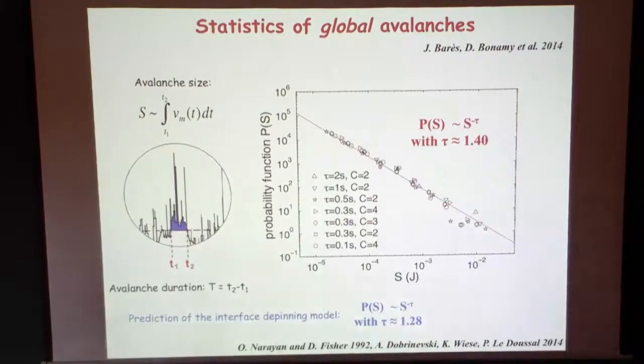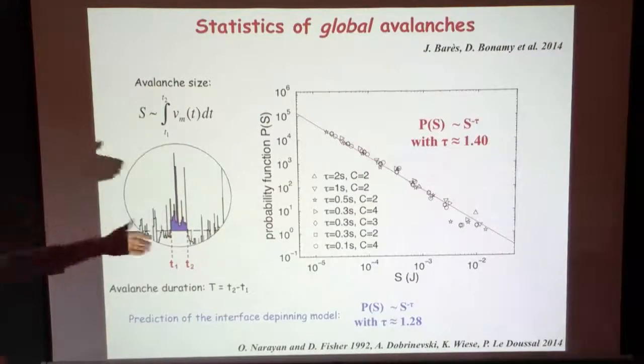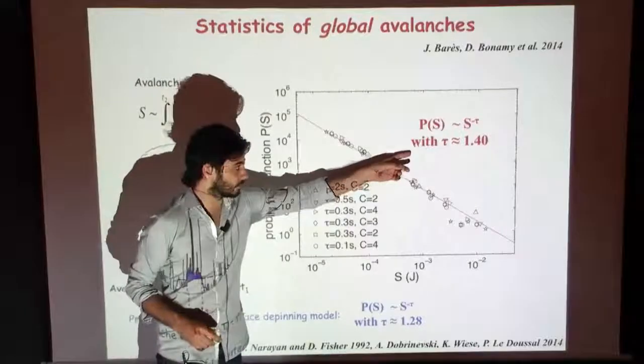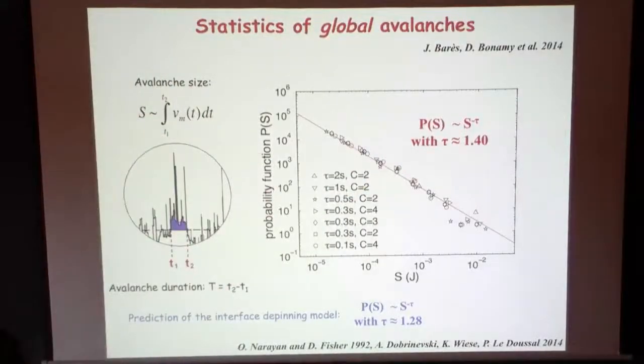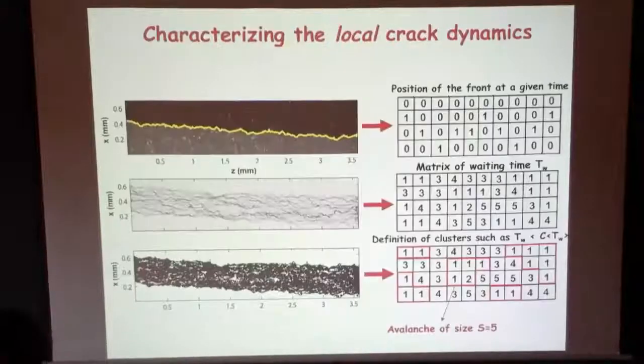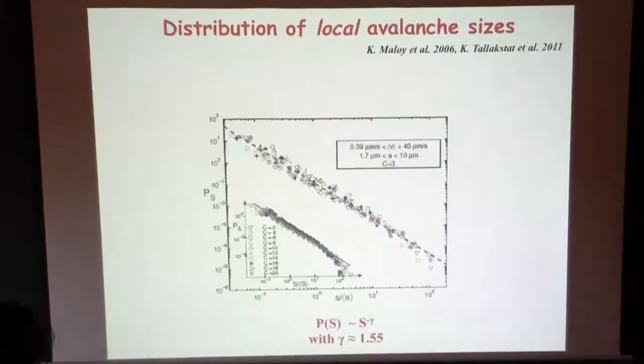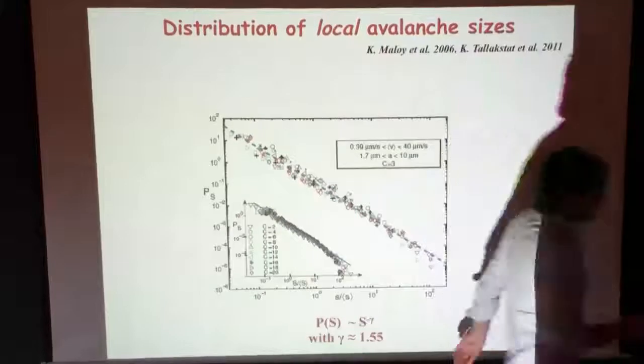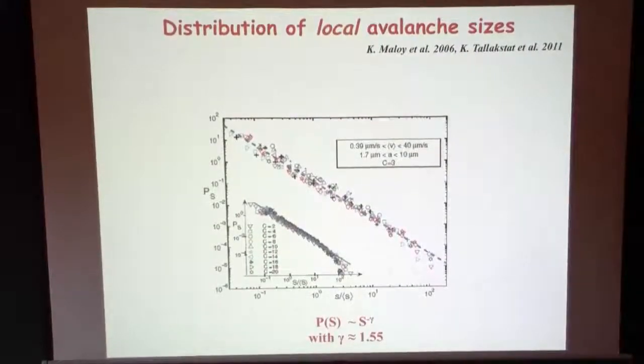I would like to make a comment on the values of the distribution of macroscopic avalanches, that is distributed with an exponent 1.4, and the distribution of local avalanches that were distributed with an exponent that is slightly larger. Actually, in this long-range elasticity problem, when I have one macroscopic avalanche, at the local scale I can have many small avalanches.